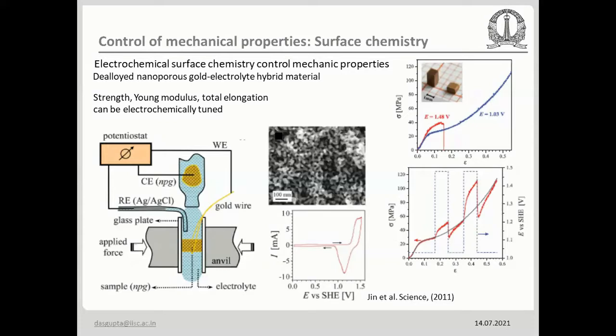Okay, and how is it made? This is typically made by a process called dealloying. Dealloying is a process of selective electrochemical leaching of the less noble material from a binary, or even ternary alloy. So typically they are alloys which are completely solid soluble. Let's assume a gold silver alloy. So we take a gold silver alloy, and then we take it into a certain electrolytic medium and apply a certain electric potential.